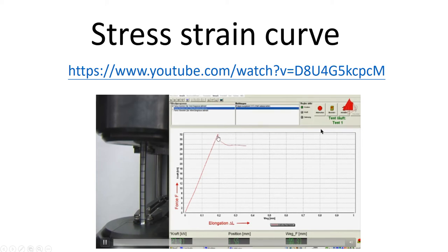If the test piece were to be unloaded now, it would not spring back to the original length, but instead show a permanent elongation. In the next stage of the tensile test, an almost constant force level with slight fluctuations occurs. This phenomenon is called the Luders effect. The plastic deformation is very long.